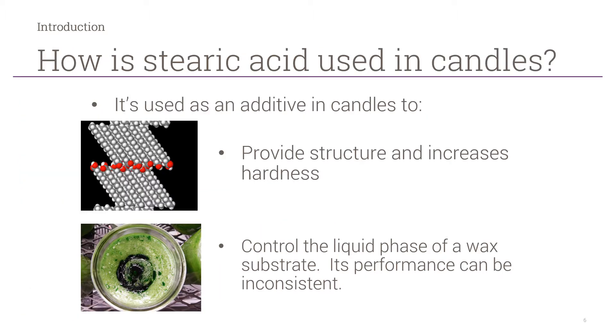I routinely use stearic acid in candles as an additive to provide structure and increase the hardness of the wax blend and to control the liquid phase of a wax substrate. As you can see in the image at the bottom left, sometimes liquid accumulates on the candle's surface as it cools. This is not desirable and sometimes it can be reduced or eliminated through the addition of stearic acid.